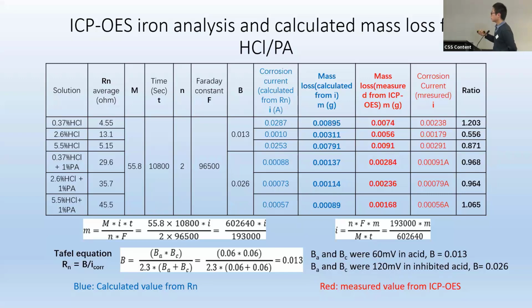Then I calculated the ratio, to compare the mass loss and to determine whether this method is working or not. And you can see those ratios are quite near to 1, which means this method is reasonably good. However, only the second one has some problem.